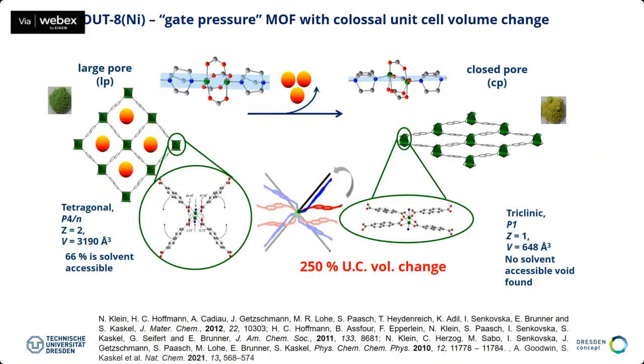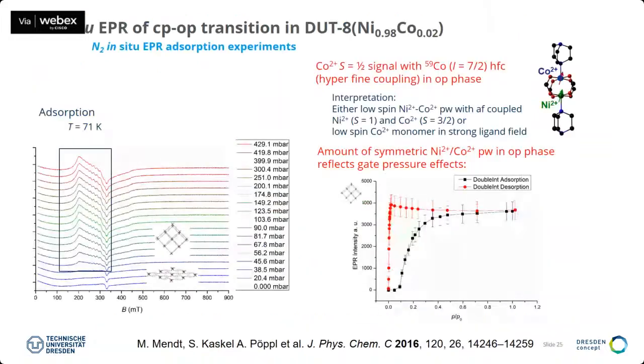Now, this deformation of the cluster is also a first signature that you can use for in situ spectroscopy. And I want to give here one example from EPR spectroscopy without going too much into the details. But EPR spectroscopy monitors the spin of a metal, essentially. And the beauty of this structure is that you can substitute some of the nickel atoms by cobalt. Here only 2% cobalt was substituted. And the cobalt has an S = 1/2 signal, basically, which is coupling with the nuclear spin of the cobalt, and therefore gives a characteristic hyperfine spectrum in the EPR spectrum.